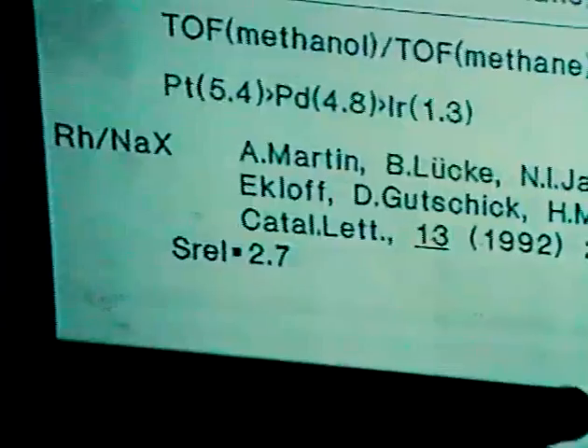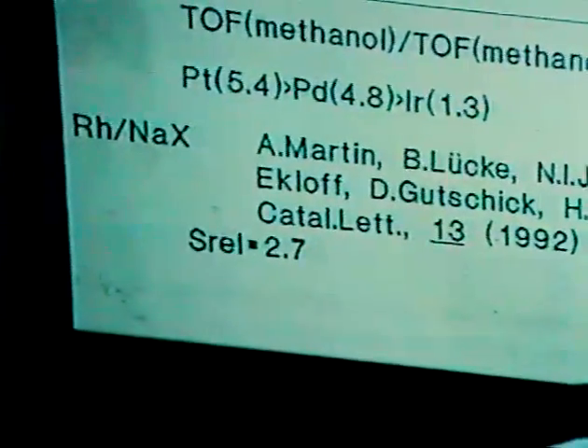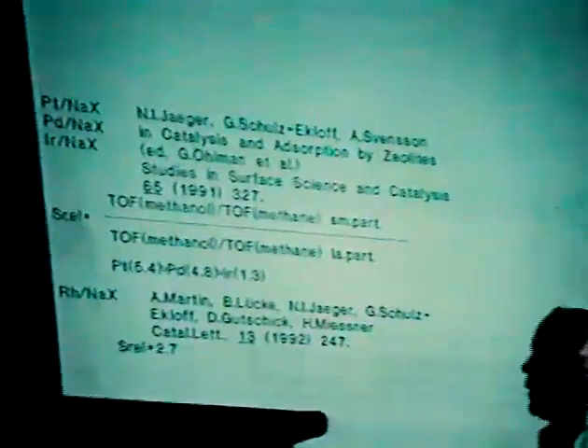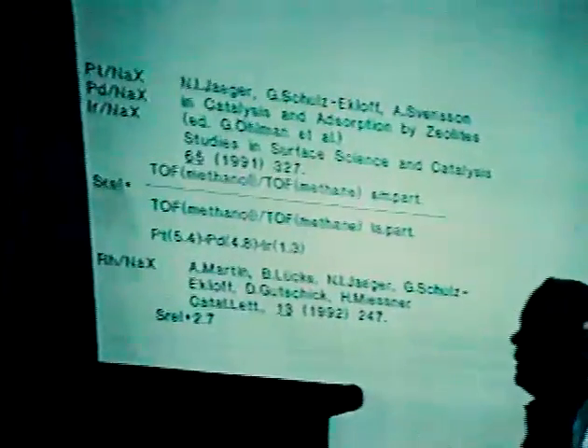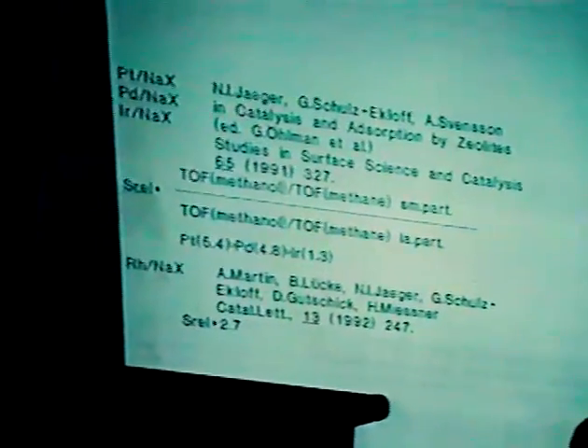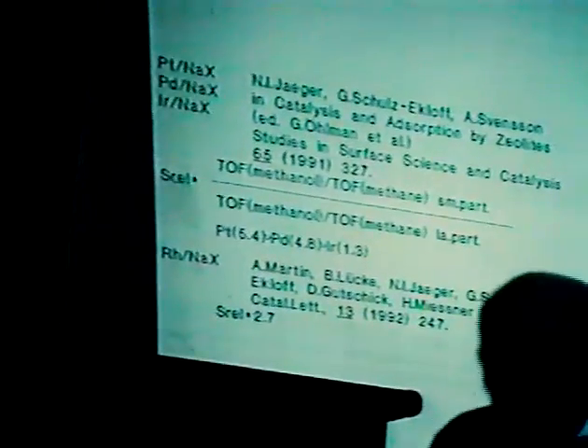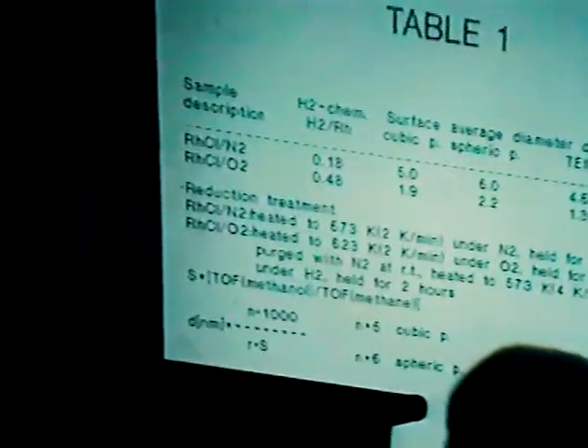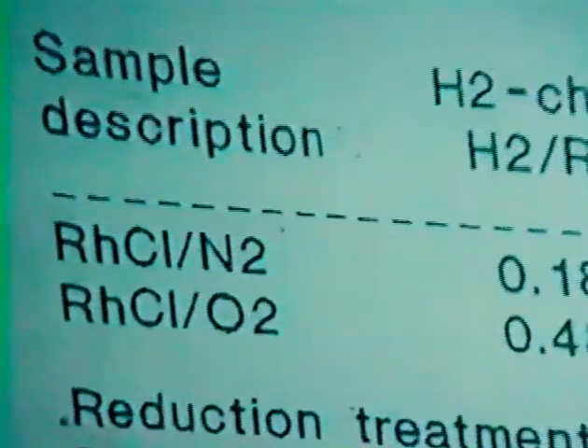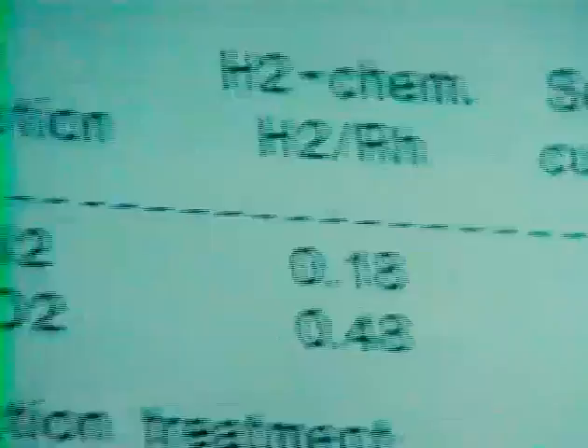In further work, we studied the same reaction on small and large particles of rhodium dispersed on sodium X zeolite, and we found the relative selectivity of 2.7, so that rhodium lies in this connection between palladium and iridium in the selectivity behavior.